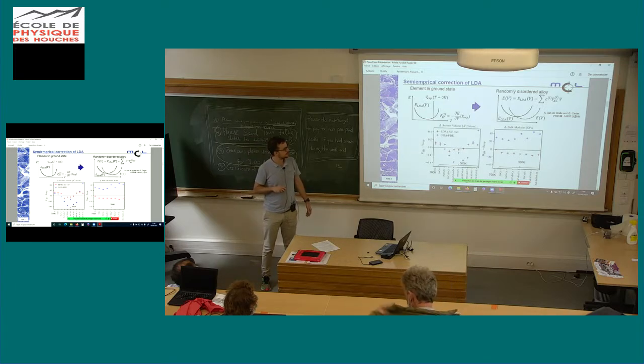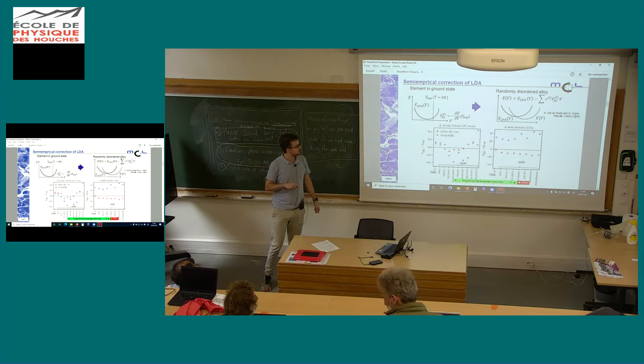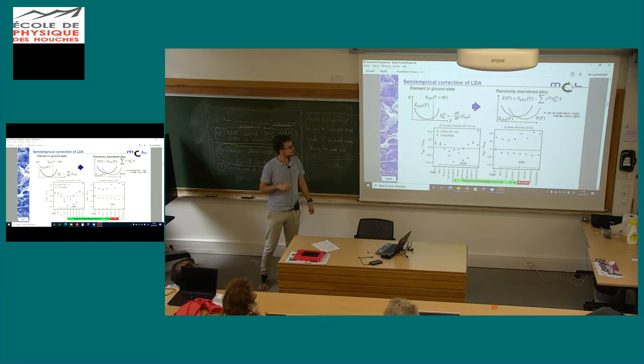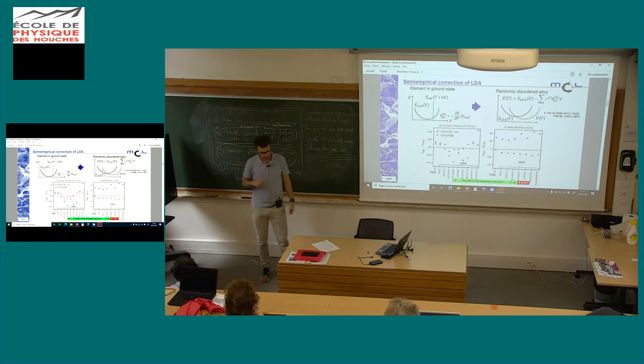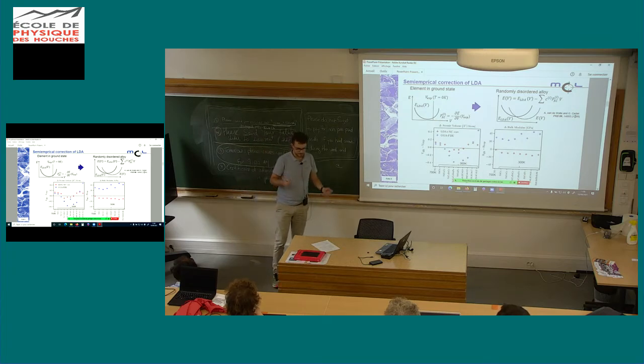We use a scheme that was proposed by Van de Walle and Ceder. We add to the total energy a concentration-weighted pressure that is element-specific and is calculated once and for all for the ground state of each element. So you effectively have to calculate the pressure at the experimental volume. The reason for that is the following. If you use LDA for most metals, you get under-predicted lattice constants. But if you use experimental values, the linear elastic properties are actually quite accurate.